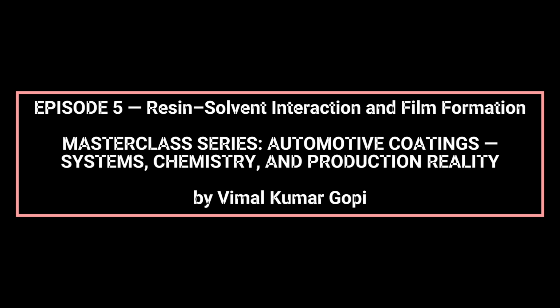At the formulation level, resin chemistry dictates compatibility with solvents. Polymers such as acrylics, polyurethanes, and polyesters require solvents of specific polarity, hydrogen bonding capability, and solubility parameters to achieve true molecular dissolution. Correct solvent-resin matching ensures homogeneous viscosity, consistent wet film spreading, and continuous film formation. Poor compatibility may result in phase separation, viscosity drift, or surface defects such as cratering, fisheyes, or flocculation.